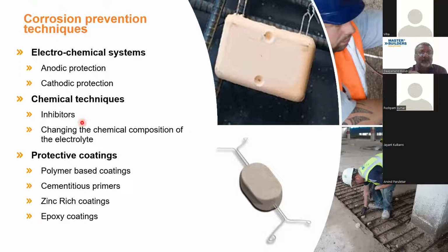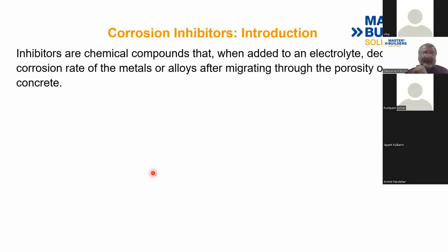Over here, I'm talking just one topic. All of these are primarily established. Anodic, cathodic protection, sacrificial anodes, we all know about that. So I'll be discussing corrosion inhibitors. So what are inhibitors? They are primarily the chemical compounds that are added to the electrolyte to decrease the corrosion rate of alloys, after migrating through the porosity of the concrete.